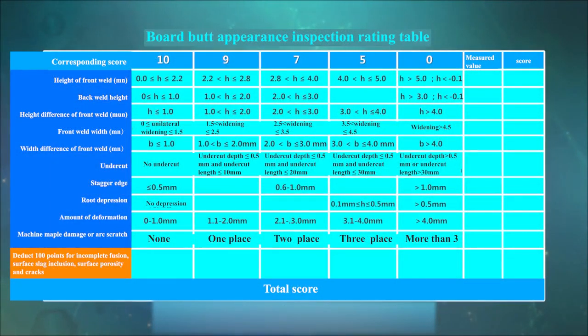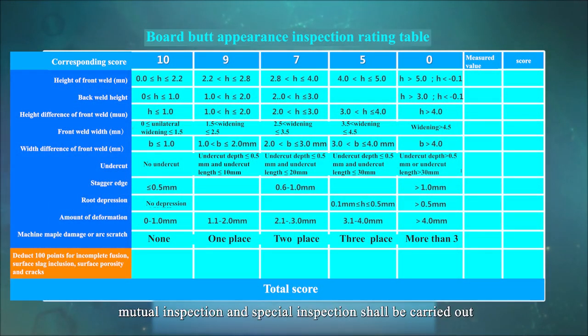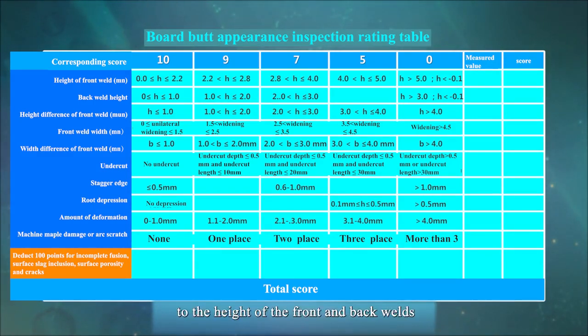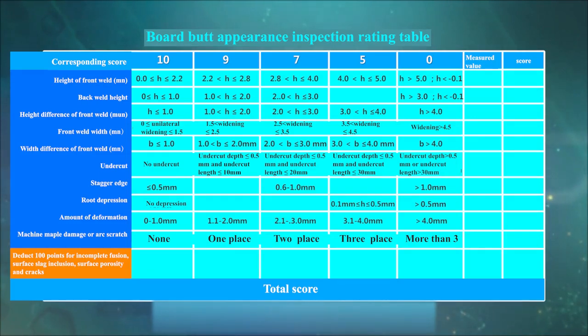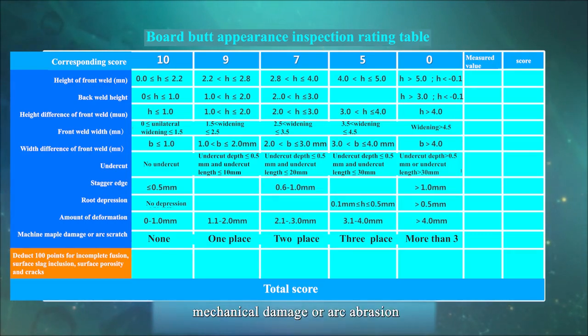At last, inspect the weld. According to the scoring standard, the self-inspection, mutual inspection, and special inspection shall be carried out one by one to check the height of the front and back welds, height difference, width difference, undercut, staggered edge amount, deformation, mechanical damage or arc abrasion, failure to fuse, surface slag inclusion, surface porosity, cracks, and so on.